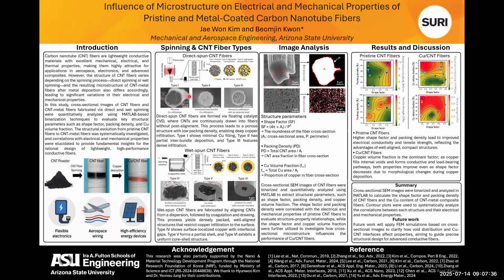Type 1 has scattered copper particles on the fiber surface. Type 2 shows partial copper penetrating between CNT bundles. And Type 3 contains copper that is uniformly distributed inside the fiber. And Type 4 has a noticeable gap between the CNT core and copper shell. And Type 5 has a reduced interfacial gap with partial infiltration. And Type 6 forms a uniform core shell structure around the CNT fiber.